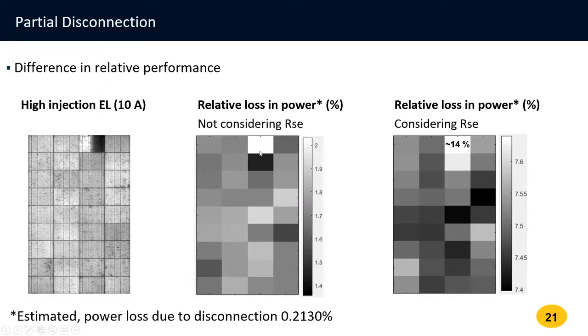That is, the electrical parameters, at least as extracted for the cell, clearly deviate substantially from the rest. And that's largely due to how a lower fraction of the cell is attempting to put through the same amount of current as the other cells, which are obviously operating at full surface area.